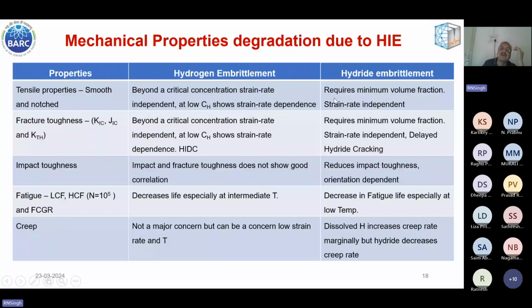Sorry, that was for hydride embrittlement; we'll go one by one. So for hydrogen embrittlement, beyond a critical concentration, it is strain rate independent. However, at low concentration, it shows strain rate dependence. The fracture toughness is also affected. Again, beyond a critical concentration, it is strain rate independent, and at low hydrogen concentration it shows strain rate dependence.